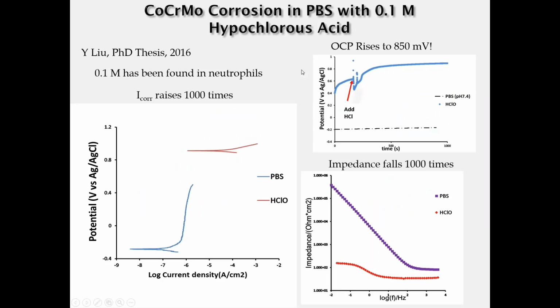Most recently, we've been looking at the role of hypochlorous acid. My PhD student, Yangping Liu, has noted in the literature that people have measured as high as 100 millimolar hypochlorous acid levels in certain circumstances of inflammation. And when you subject cobalt chromium molybdenum to those conditions, this red line shows up. That is, the open circuit potential for cobalt chromium rises to almost 900 millivolts. And the corrosion current is up here about 3 orders of magnitude higher, about 1,000 times higher than when in